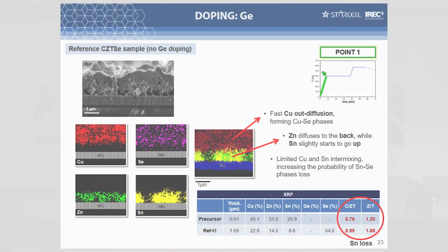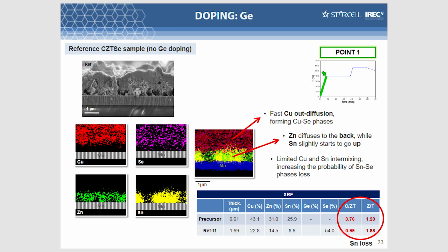And stopping here at the first point where kesterite is starting to be formed, when we don't use germanium, basically what we observe is that we have a strong separation of copper phases from the other phases. We don't have a very good mixture between copper, zinc and tin. And we have a lot of tin loss. Basically, in this process, when we don't include germanium, a lot of tin is lost in the atmosphere.